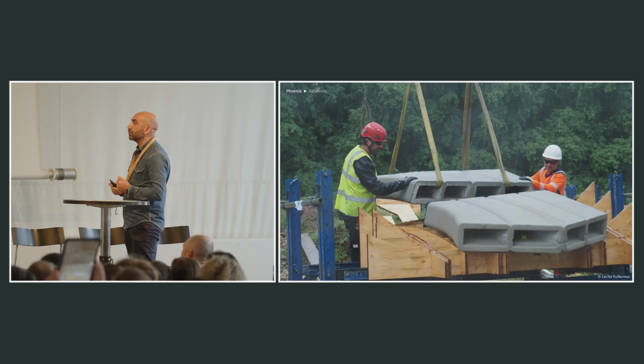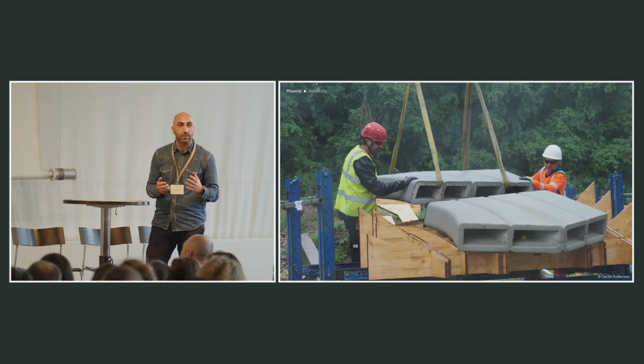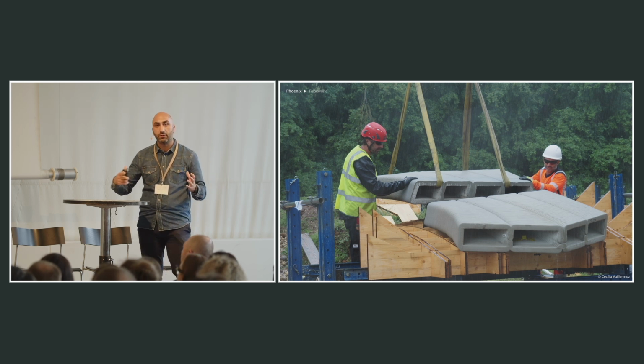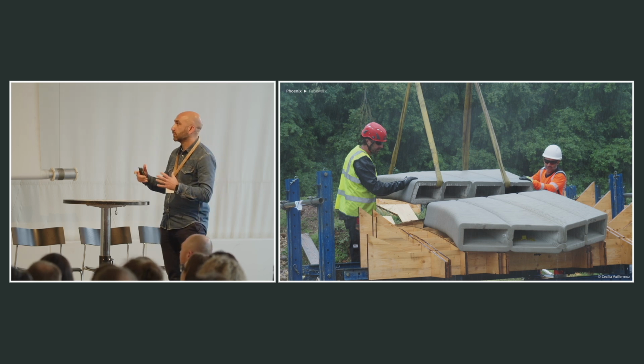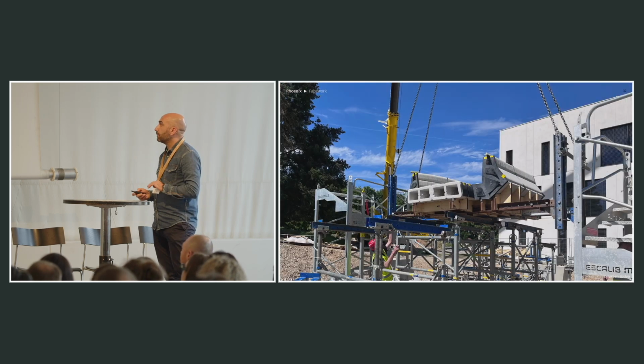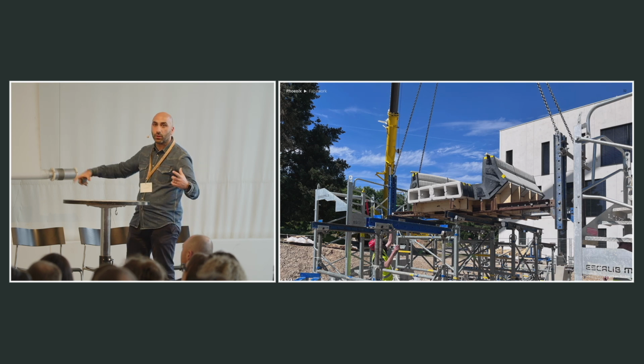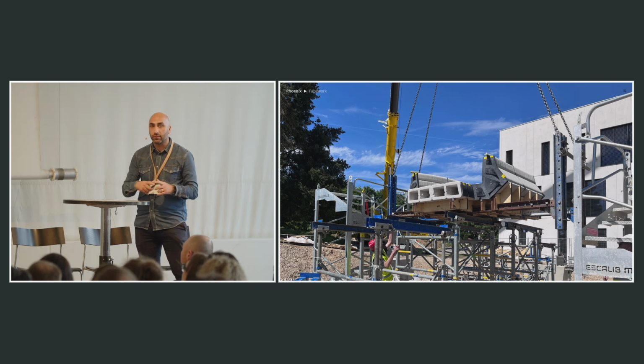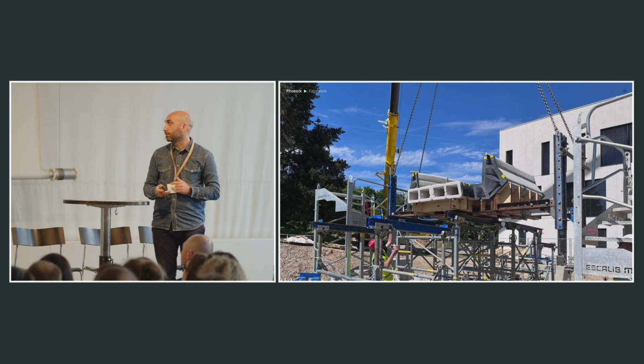And we also increase the precision during the assembly because we pre-assemble these cassettes with a few components on top, and then we lift them up on top of Doka towers, which were placed along the skeleton of the structure.